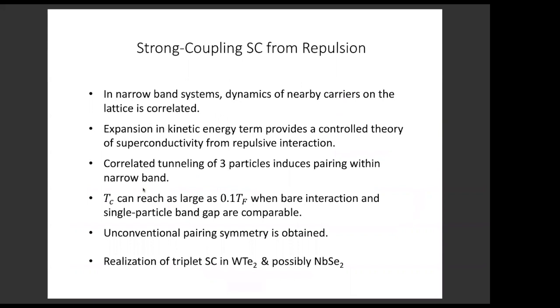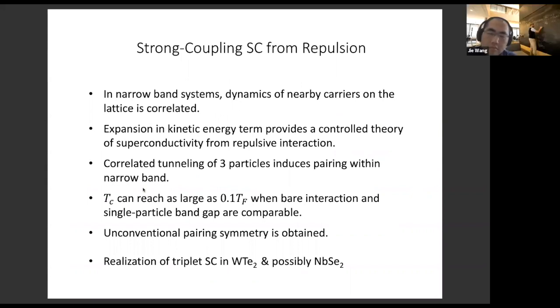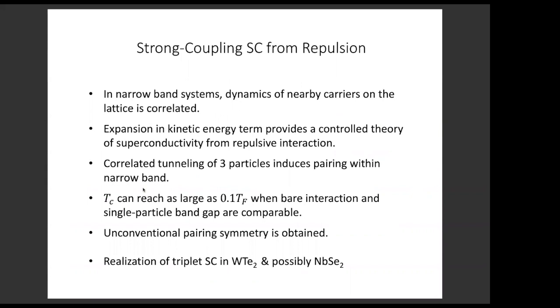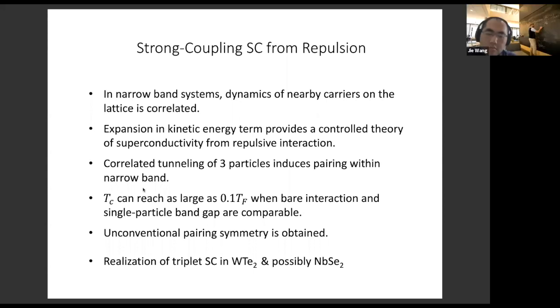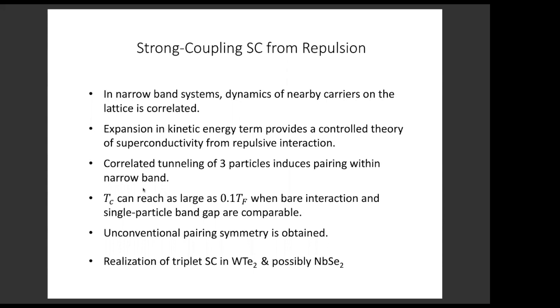So okay, I think I'll just leave it here. I've already summarized the theoretical work, and finally, I just want to mention that in addition to tungsten ditelluride, we believe that this triplet superconductivity from this interband renormalization can also possibly be relevant to niobium diselenide. There's a recent experiment from Cornell showing that as a function of the in-plane magnetic field, there's a hysteresis in the superconducting gap. So again, the triplet order parameter allows the D vector to reorient. So this may possibly explain also niobium diselenide. Okay, thank you.